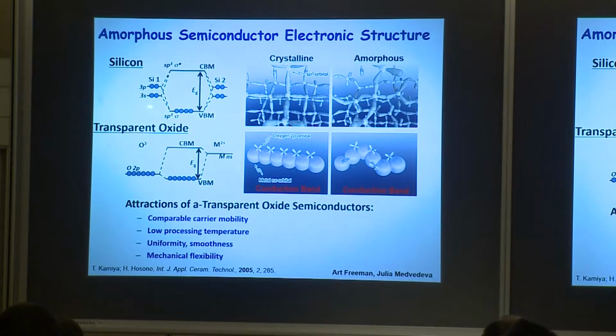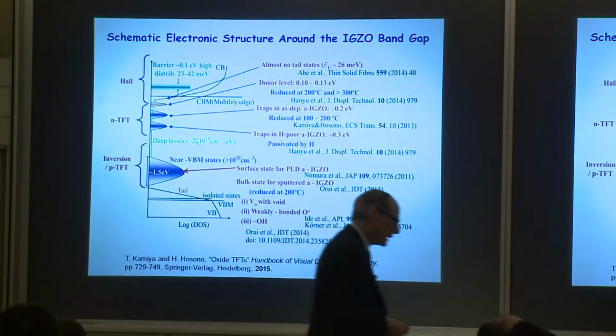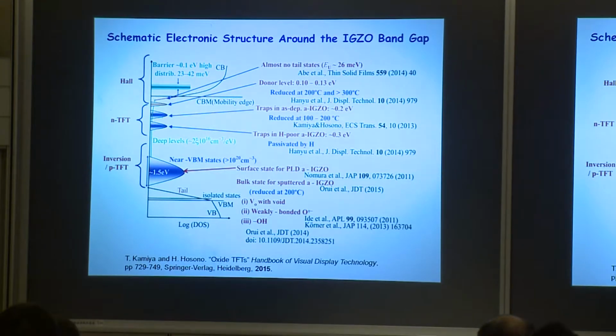Another way of looking at what's going on is here's silicon, and of course crystalline silicon has this nice sp3 orbital band structure. You start clipping the bonds by making it amorphous, and of course the conductivity and the mobility nosedive. On the other hand, with the oxides, here we have our S states, our S orbitals that are going to be the electron carriers, and if we bend them around, as long as they're touching, we still have good mobility.